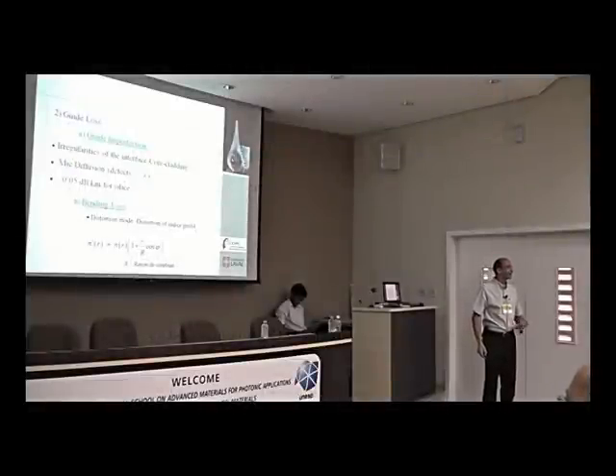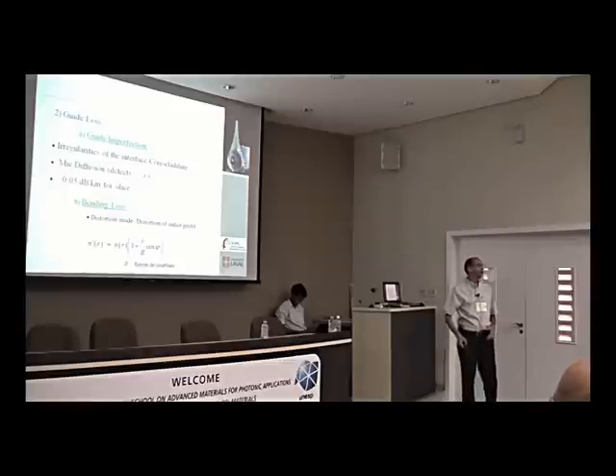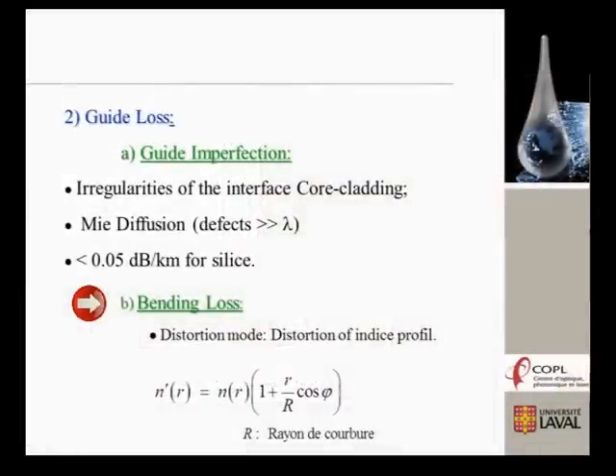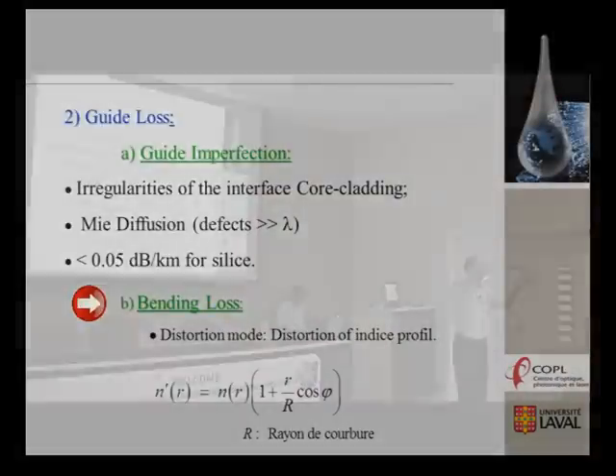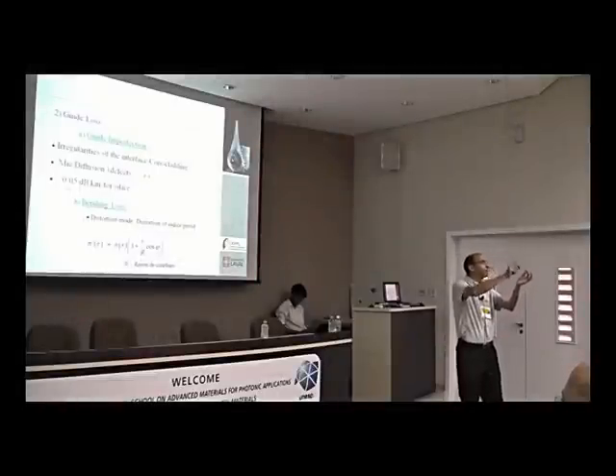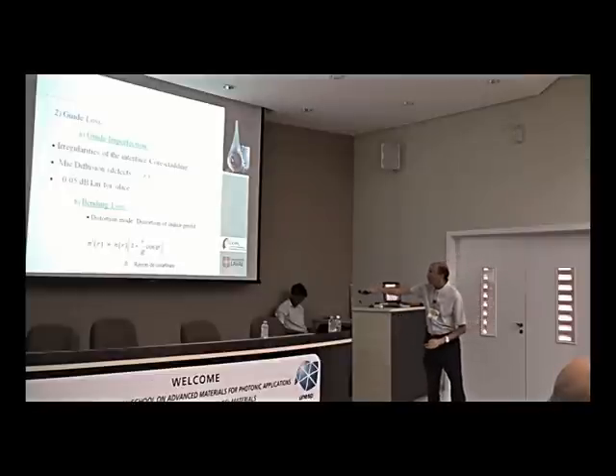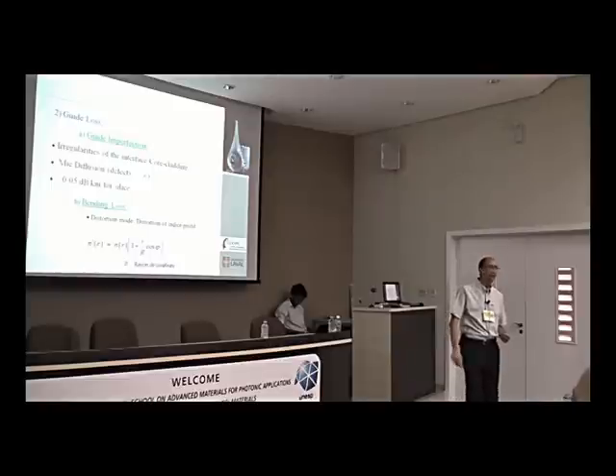When we solve this problem again, we have another one. This time it is coming from the bending losses. Bending losses, as I said in the beginning: the fiber is a glass core and cladding with a jacket of polymers, and when you bend your fiber, depending on the angle or radius of your fiber, sometimes we are going thinner, you will have some distortion. The distortion due to the bending comes from distortion of the profile of the refractive index, which can be explained by this equation.